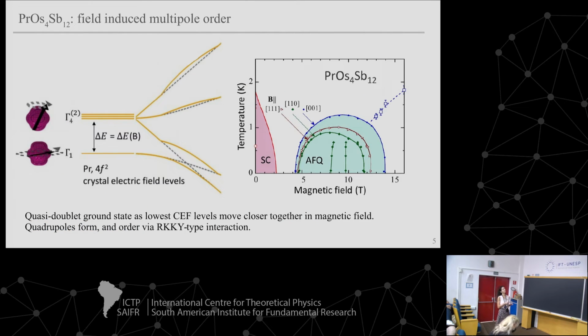Okay, a more realistic crystal field level scheme. This we did just with mean field theory. So there's the crystal field term in the Hamiltonian, and now there's a quadrupole term in the Hamiltonian that gives you the interactions here, and the anticrossing. And what we understand is that outside of this antiferroquadrupolar region, we've just got a usual Boltzmann-type excitation between the crystal field levels. And then once you get inside this region, or once you get close enough, you actually have a superposition of these two states rather than an excitation from one to the other. And that's what allows us to have the quadrupole ordering in this case.